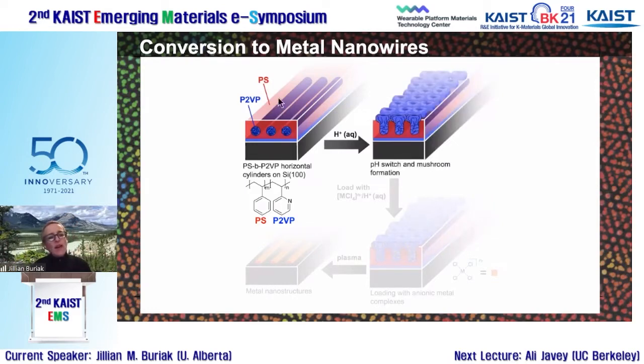And so what we found is that when you dip this into an acid solution, the acid will find its way through defects in the polystyrene and will protonate the polyvinyl pyridine. It's simply a base. So the polyvinyl pyridine, which is encapsulated there in this thin layer, becomes protonated and undergoes a massive volume expansion. And so at that point, it's accessible to us because there it is on the surface.